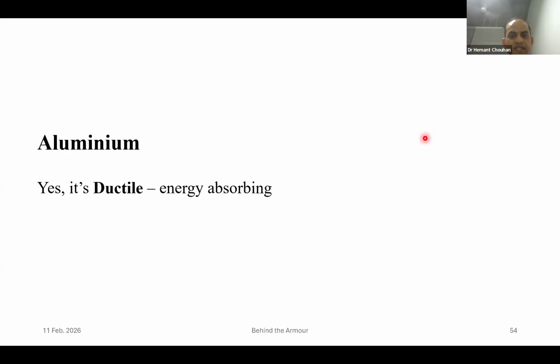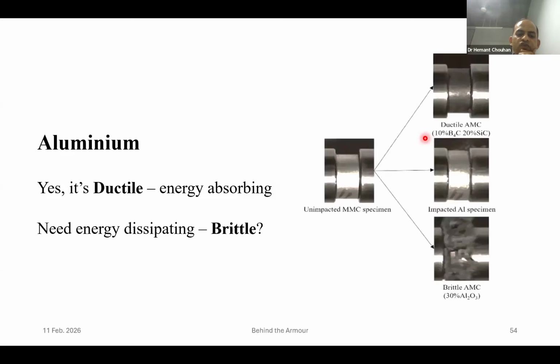And similar studies, if someone is interested: aluminium generally is an energy absorbing ductile material. But if you wish to make a brittle material, something like glass which will shatter, under the high strain rate regime I can design both. Now, this is my aluminium specimen with high hardness particles. It is not deforming. If it is pure aluminium, it deforms very well for the same impact energy, and with the help of suitable additives we can make it brittle as well.